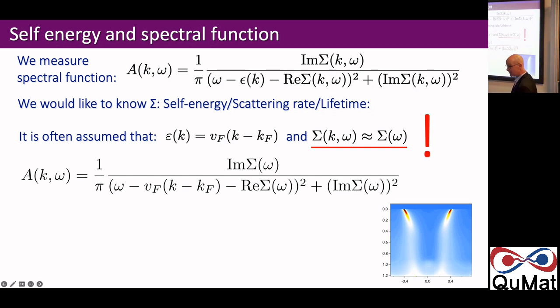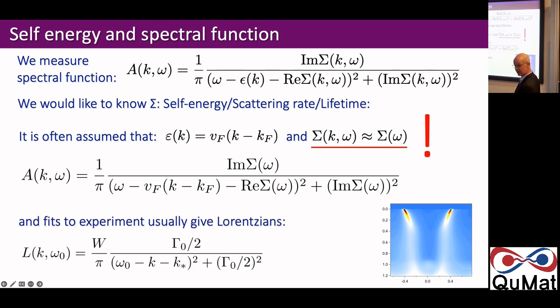And if you're an experimentalist and used to fitting data, you will recognize this formula as a Lorentzian. So it's a Lorentzian where the imaginary part of the self-energy is the half width. If we would cut through this thing and get a peak, it's the half width of that peak, which we need to multiply by some velocity to get it in eV terms, but we can just quote it in reciprocal angstrom terms, and then we don't care what self-energy someone wants to prefer, or velocity they want to prefer.